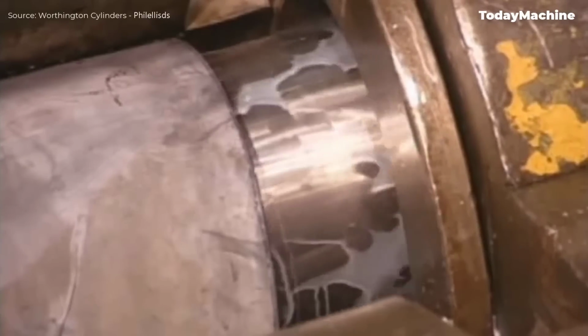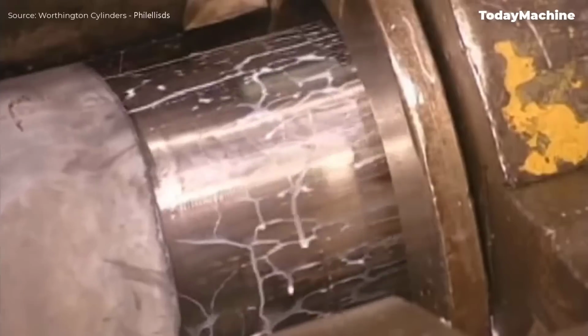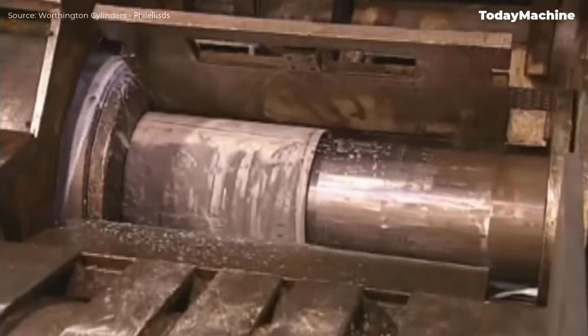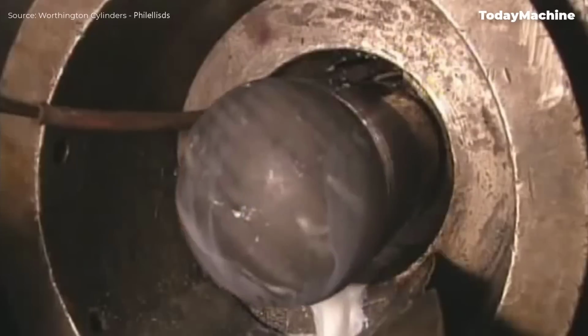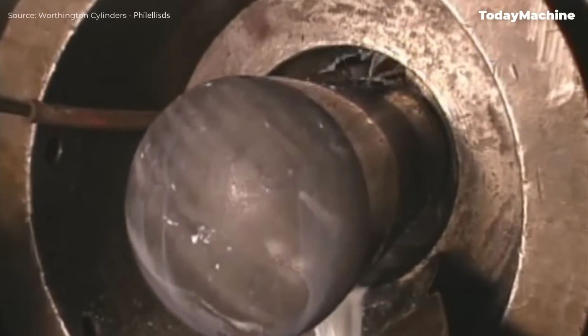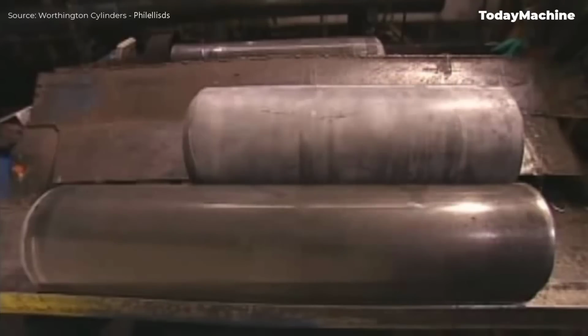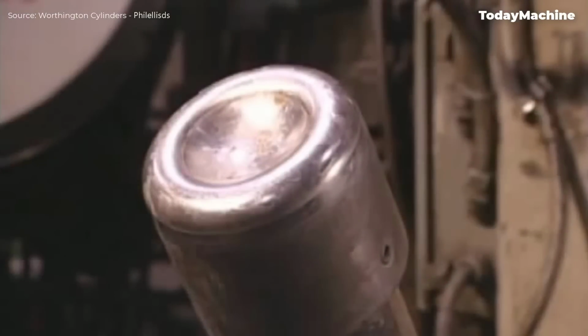Typically, 3 draws are required to produce Scuba cylinders, with each draw reducing the material's diameter and thickness by approximately 60%. This deep draw and ironing process is crucial in achieving the desired wall thickness and buoyancy characteristics essential for Scuba cylinders.